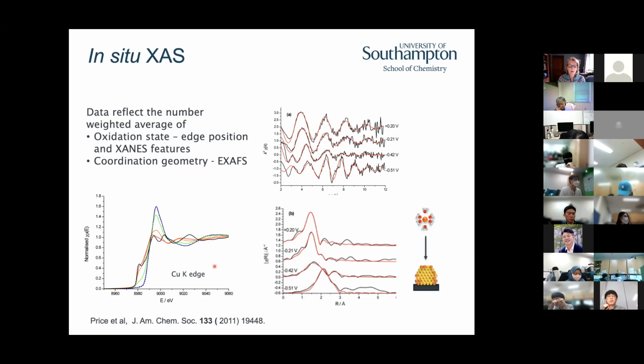So what are we doing? We can collect the data either from the perspective of the gold atoms, or from the perspective of the copper atoms. Let's look first at the perspective of the copper. This is the X-ray absorption spectrum, and we're going to look in the XANES region. As we deposit the copper, the dashed line and the blue line are the spectrum of the copper when it's just in solution, the solvated copper 2+ ions. The black line is the spectrum of copper metal, a foil. As we change the potential and deposit the copper onto the gold, the spectrum shifts from being of the copper species in solution to approaching something like the metal foil.